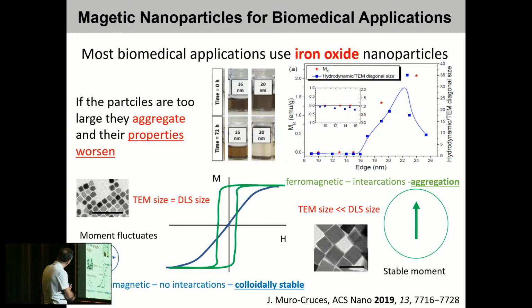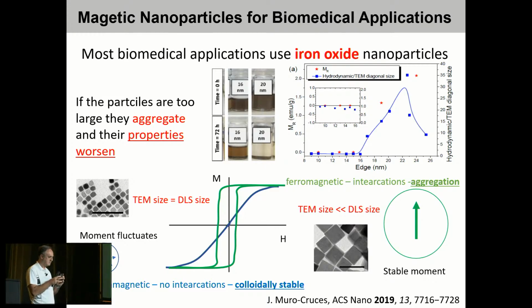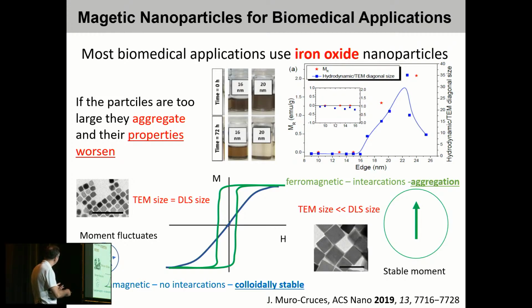This is the ratio of the TEM size by the size measured by light scattering, which gives the size of clusters if they are formed, not the size of the nanoparticles themselves. And we see here that if the particles are small, the ratio is 1. The ratio of the TEM size and the DLS size is the same. But as the particles become larger, the light scattering size starts to increase, meaning that these particles have agglomerated. And when they agglomerate, their properties usually worsen. And actually, they cannot flow in the biological media as easily as single nanoparticles.